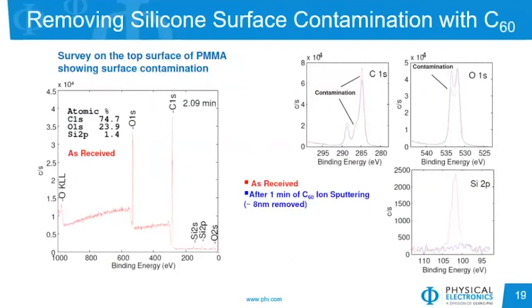To start with, we have a PMMA surface that is showing surface contamination of some silicones. We can clean this off using C60 cluster, for example. As you can see in the spectra for C1s, once we have cleaned the material off, which is the blue spectrum, we do see more of a shoulder at around 285 that is representative of the structure of PMMA. We also see an increase in the oxygen 1s peak at higher binding energy, which is consistent with that of a cleaned PMMA. We also see the silicon concentration has been effectively removed after the C60 sputtering, showing that we can clean off the surface contaminant but preserve the chemistry of the underlying material. If we tried to do this with a monoatomic argon, we would most likely damage all of these and leave us with just a graphitized carbon.